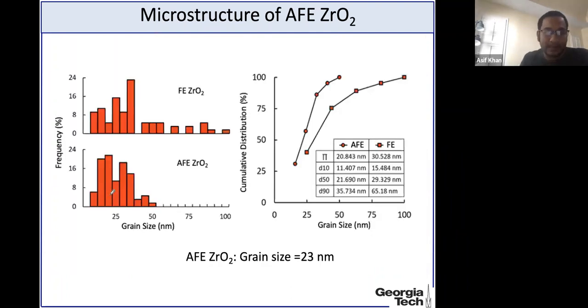So if I look at the grain size distribution over here, for zirconia, it is a pretty broad peak with probably a geometric mean of around 23 nanometers. Okay, so it's probably here, 23 nanometers. And some grains are pretty large over here.